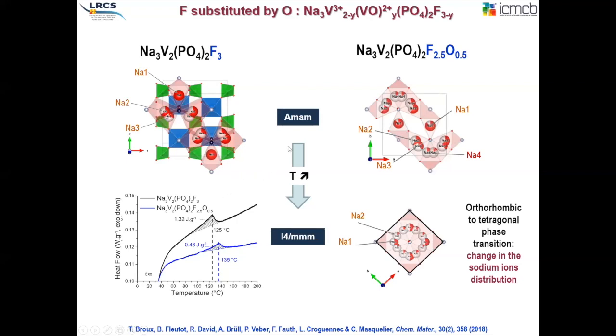The phase transformation from the Amam orthorhombic space group to the tetragonal I4/MMM takes place at slightly different temperatures. So this is also a way to quantify the amount of oxygen in a given cathode, I would say, for this family. And also the energy related to this transformation depends on the oxygen versus fluorine ratio.